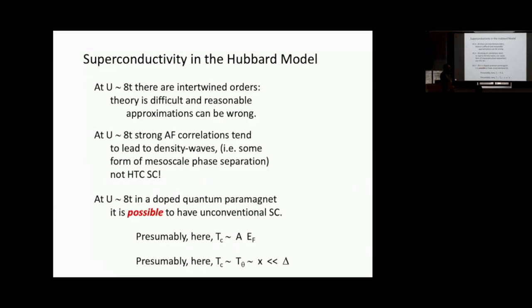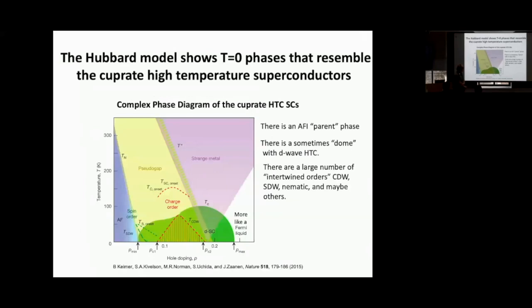Okay. So at any rate, I think this idea of a doped paramagnet has at least some of the appeals that are generic that came from the idea of a doped RVB state. All right, so let's see. So here's what I hope that we see, that the Hubbard model has sort of the same parent antiferromagnetic ordered insulating state. It can sometimes have a D-wave high temperature superconducting dome. It very robustly has a large number of intertwined orders, and that doping a quantum paramagnet is a good way to get a high temperature superconductor. Okay, good.